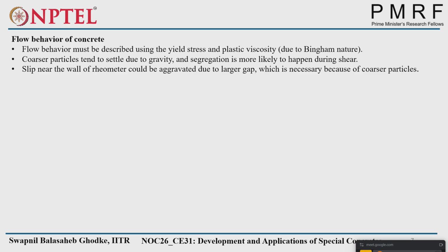So we saw cementitious paste. What about the concrete? Flow behavior must be described using yield stress and plastic viscosity due to Bingham nature. In the case of concrete, due to the coarser particles, there is a possibility of settling down due to gravity, and segregation is more likely to happen during shear, right? If you are providing shear or shear rate, there is a high possibility of segregation. Another problem is slip. We have the container. If you saw in the last video, we have a large container, and we are providing the vane shear.